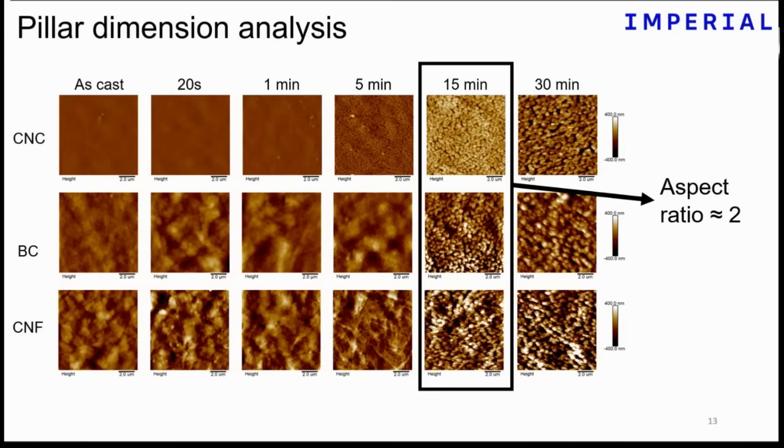And I guess the other thing I wanted to say is that for the coating itself, the length scale on the right side is 4 microns here, but the vertical dimension from bottom to top is about a micron. So the coatings are exceptionally thin, such that they are actually transparent. That's the other thing we wanted: to be able to apply them on a window pane so that you can see through, right? Otherwise, it would not be acceptable to a consumer.